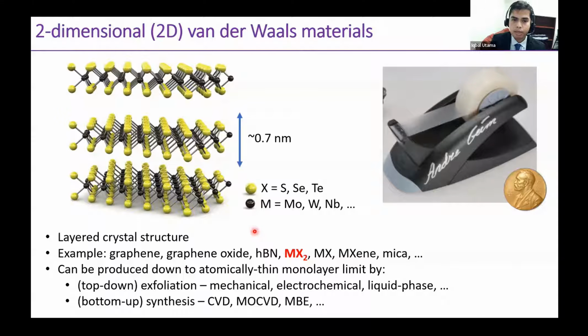And there are various ways one can produce these materials in their monolayer limit. That includes the top-down approach that incorporates some type of exfoliation method, which includes mechanical exfoliation, such as the use of the commercial Scotch tape method in this celebrated experiment popularized by the group in Manchester, where they start with graphite, like what you typically see in pencil lead, then peel them down sequentially until they get really just one atom thick material. They got a Nobel Prize out of these experiments by studying the unique electrical properties of those materials. On the other hand, you can also perform a bottom-up method that involves synthesis, such as chemical vapor deposition, where you can get scalable monolayers on a larger scale.